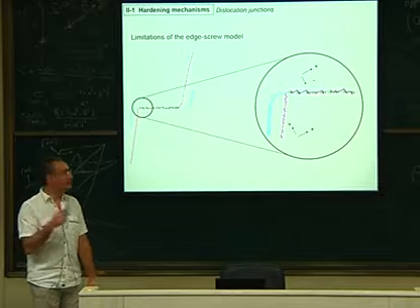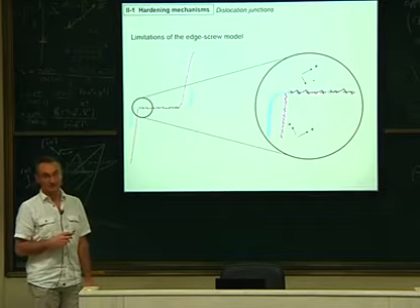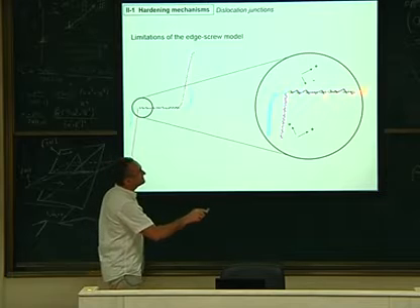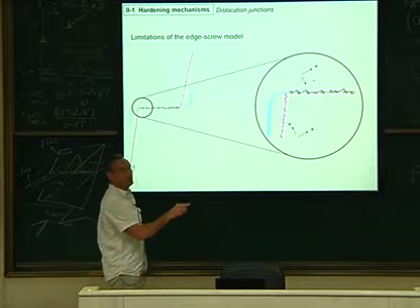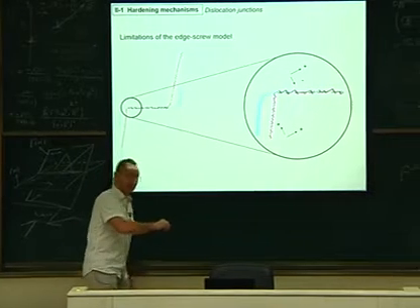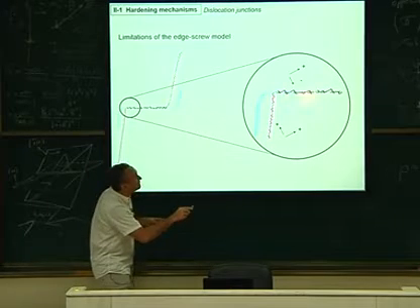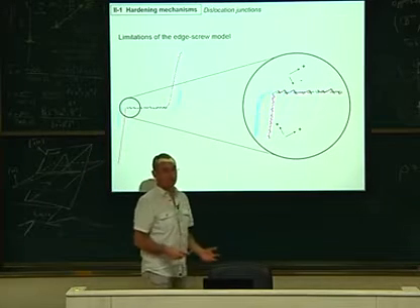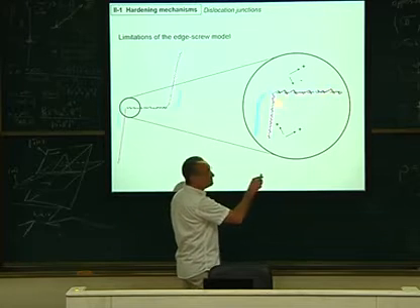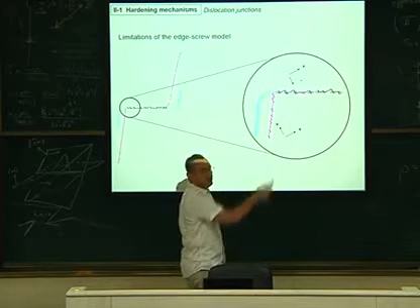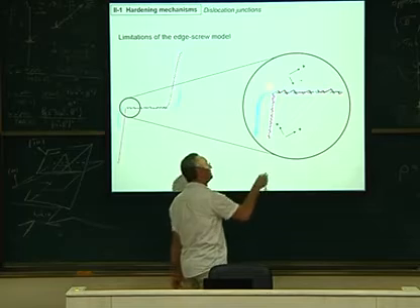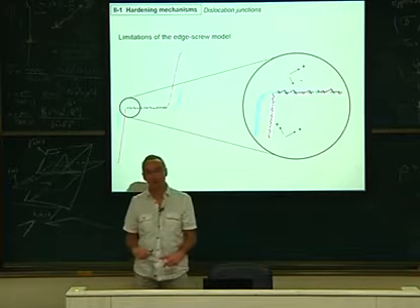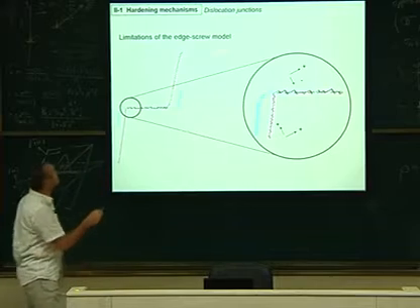The junction I cannot handle with 3D is the glissile junction. Because for the glissile junction, I should be able to change this dislocation into a new one whose Burgers vector will be in the same plane. So in my line here, I will have a change of Burgers vector so that it can glide in the plane. It's not possible in my code today. Today, this pink line will remain there and will be able to move only in the initial plane it is in, not in another one. The blue can stay in the horizontal one, but not with the red. So it will not be a junction. So the glissile junction is not accessible with this edge-screw model.